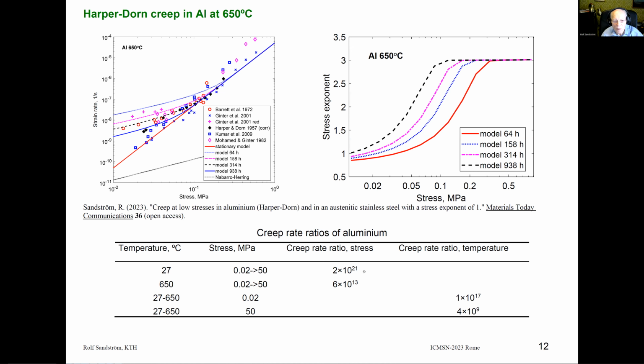You can extrapolate the results also in this case by many, many orders of magnitude, and the results still work because, as you saw previously, the aluminium model can be used at room temperature and at high stresses. So it verifies the validity of the model.